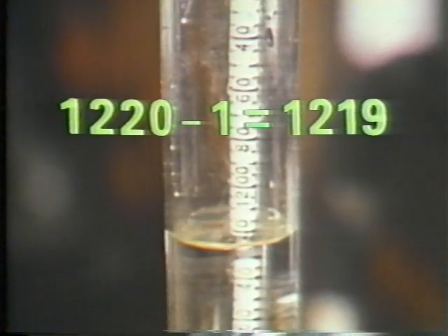The thermometer shows a temperature of 73 degrees Fahrenheit, approximately 4 degrees colder than the base temperature of 77 degrees. The scale on the right-hand side of the thermometer indicates the specific gravity correction factor for temperatures above or below 77 degrees. This temperature is halfway between 0 and minus 2 on the scale, so the correction factor is minus 1. A reading of 1220 with a minus 1 correction factor gives a corrected reading of 1219.